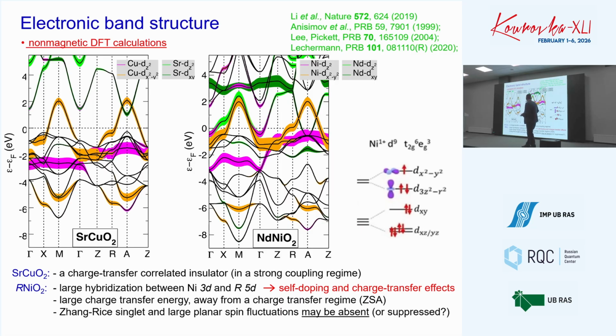What we do see is that the electronic structure in the case of nickelates is somewhat more complex, in the sense that there is a self-doping due to the shift of the rare earth 5d states. They shift below the Fermi level and start to contribute to the Fermi surface. This is the first point. The second point is that the oxygen states appear deep below in energy, which means this material behaves more like a Mott-type system, although cuprates are charge-transfer insulators. As soon as you introduce correlations, cuprates will become insulators. This one possibly not, due to the contribution of the rare earth d states at the Fermi level.